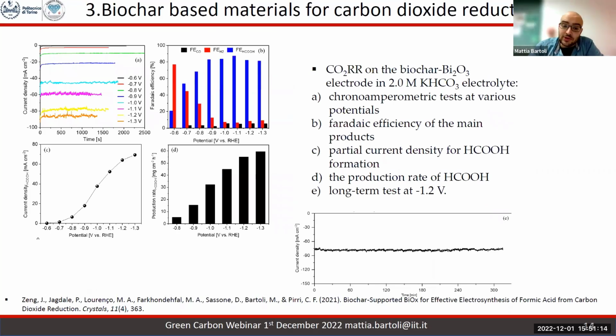So, the core of the work, the electrochemical part, this material performing amazingly. The Faradaic efficiency of the overall process is quite high, close to 90%, and the selectivity towards formic acid is very remarkable, up to 80%, and the stability over time that you can see in the bottom part of the slide is quite high, up to 5 hours. Also, the current density reached is considerably high, around 100 milliamperes per square centimeter, and it increases with the potential.